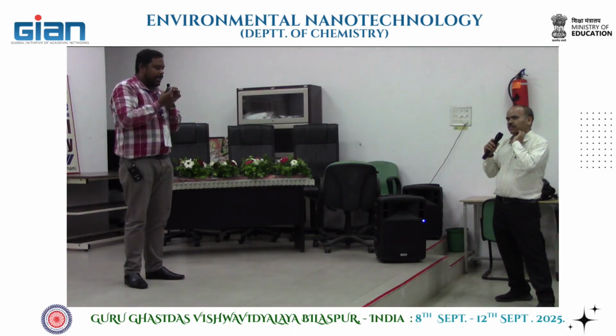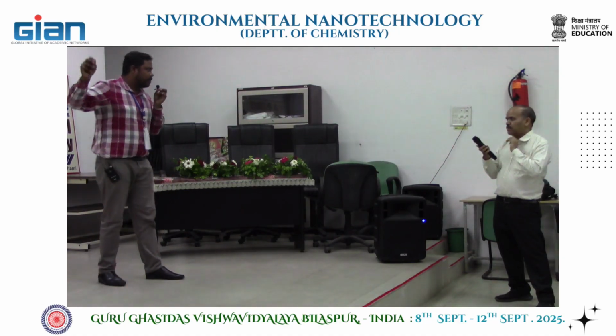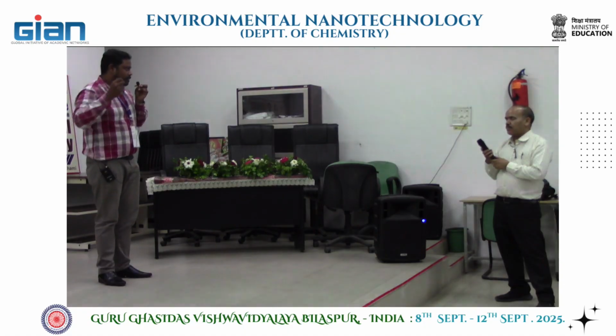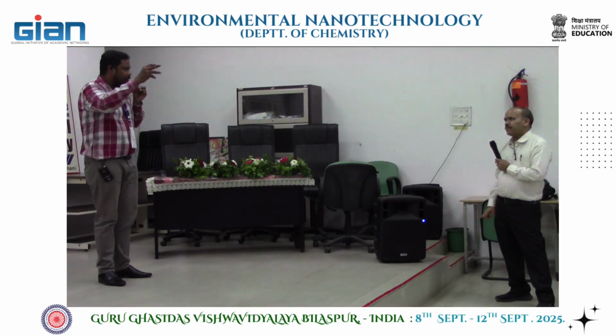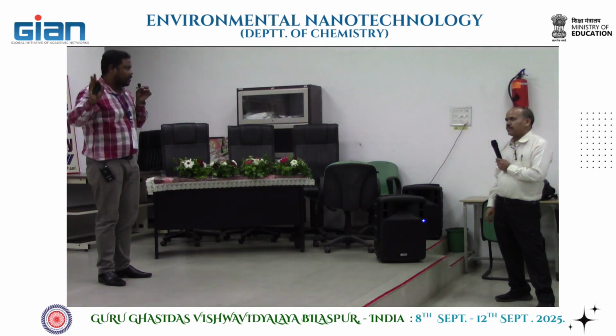That's why, like this imine cage, we are keeping it for 3 days, 4 days. We are simply rotating it for 4 days. Then we check by NMR whether it is a mixture or a single product. When it is a single product, at that point we stop the reaction and isolate the compound.